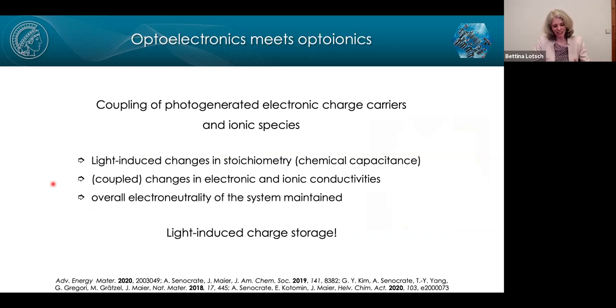And optoionics is something that has been discovered, I would say, by my colleague Joachim Maier in Stuttgart, and also Michael Grätzel, in MAPI-type halide perovskites quite recently. So hole trapping in MAPI-type hybrid perovskites was described, and it was shown that this is an optoionic effect. Whether this is truly an optoionic effect here or not is a question I cannot answer at this stage, but what I can say is that what we observe in PHI is basically light-induced changes in stoichiometry. So remember, we have a change in the potassium content of the system.